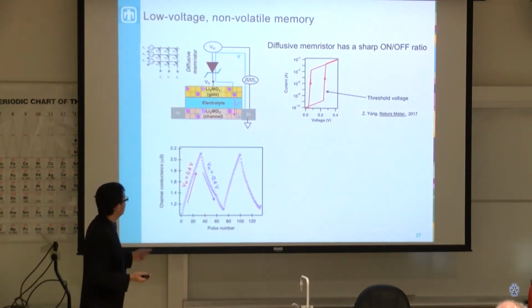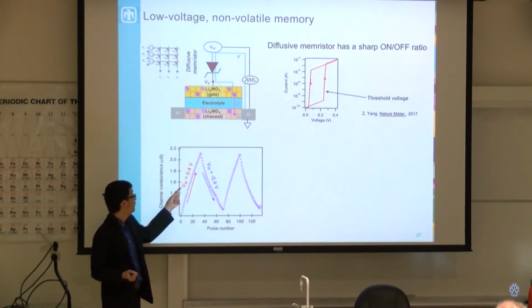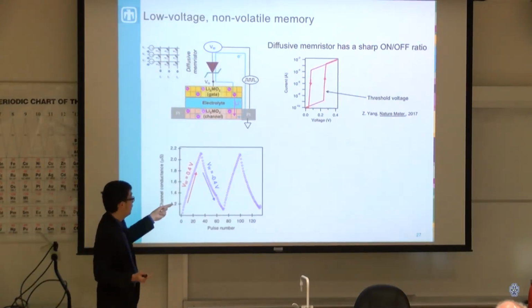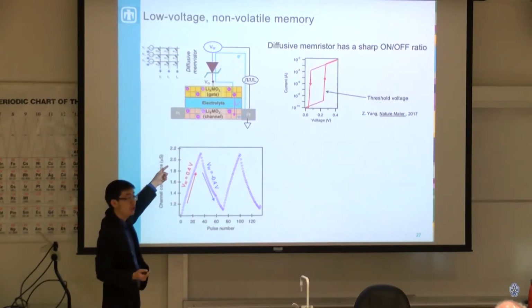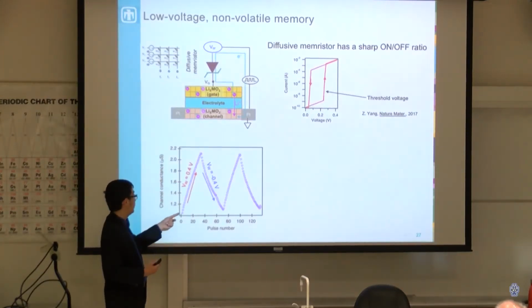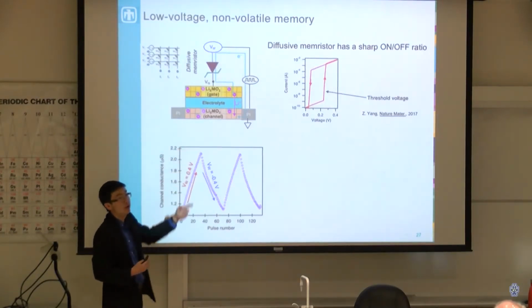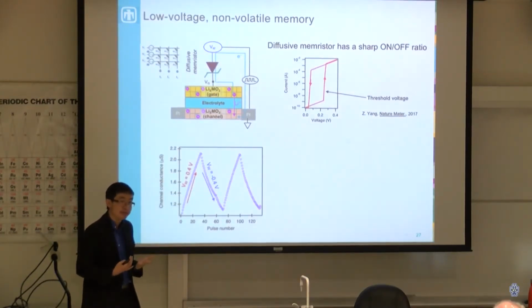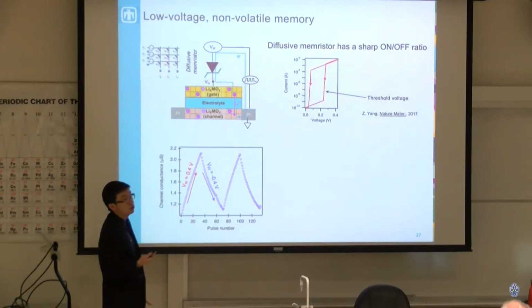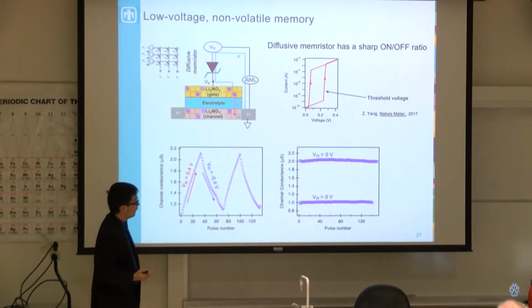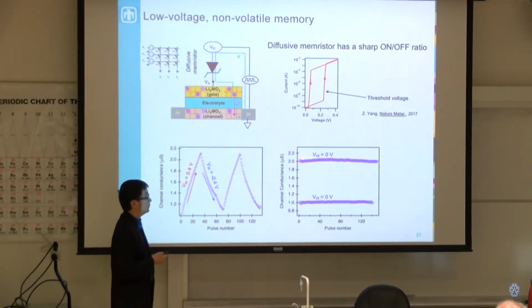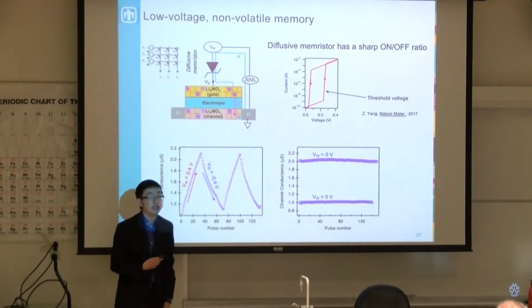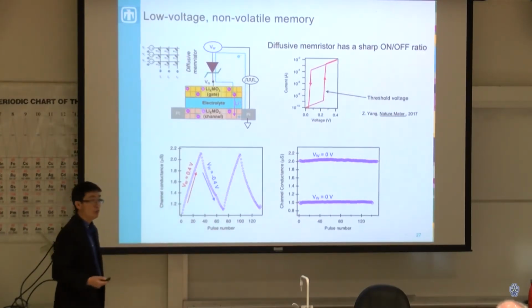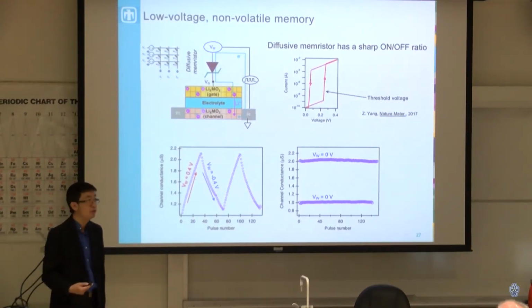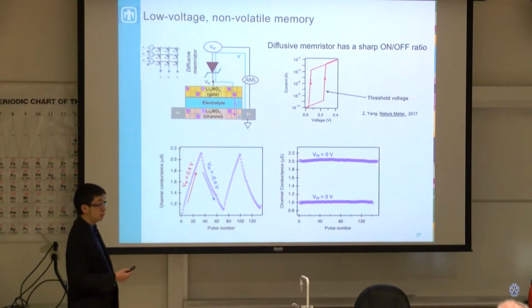So what we can do is that when we apply just a couple hundred millivolts, say 400 millivolts, across this device, we're able to change the conductivity of this channel. So we're moving electrons and lithium so that we can change the conductivity of the channel, and as a result, change the state, the synaptic weights, the weights that we use to do computation. And it's also non-volatile in the sense that when we shut off this switch, we can prevent this device from self-discharging. So it's able to maintain the state even when we remove the voltage that we use to program this device.